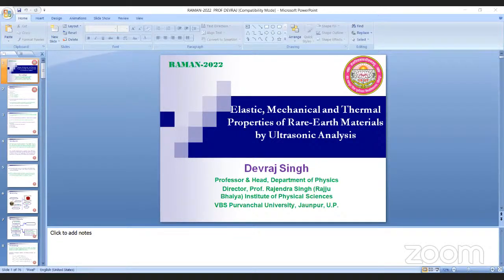If you study the body centered or face centered, then you will see the value of the nearest neighbor distance is different. We use fitting parameters, which is the hardness parameter. Next is density. From these three parameters we find the ultrasonic velocity, and ultrasonic velocity is applied to find the thermal conductivity and other parameters, specific heat, energy density, and finally ultrasonic attenuation.